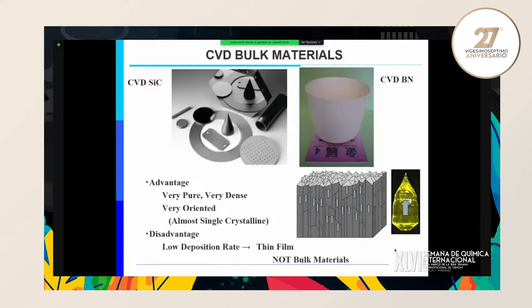So the advantage of CVD is we can make very pure, very dense, and very oriented, almost single crystalline material. The disadvantage of CVD is that the deposition rate is low, and it is usually used to make thin films, not bulk materials. But if we have a good precursor like silicon tetrachloride or a boron halide, we can make bulky materials, though that still needs a long time. But with only not so reactive precursors, bulky oxide, for example, has never been prepared by CVD.